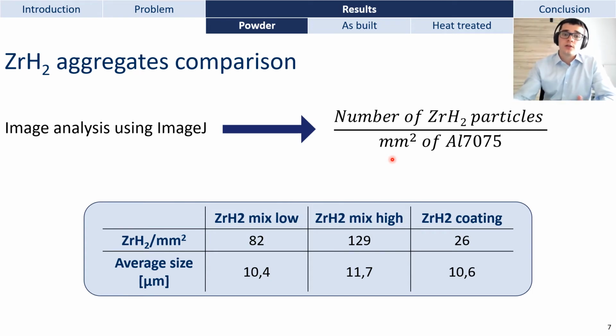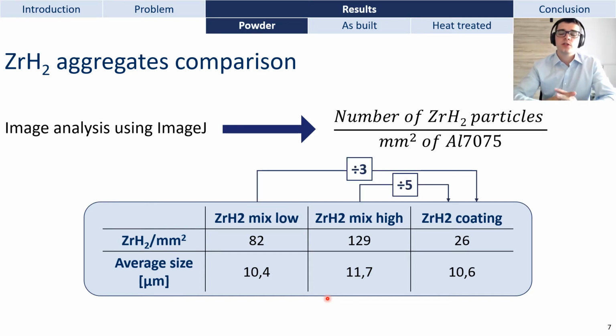We are also computing the average size of these particles, and you can see that for the three different alloys, it is roughly the same, around 10 microns, corresponding to the size of the zirconium hydride powder. What is really interesting there is that the zirconium coated powder exhibits respectively 3 and 5 times fewer particles than the low content mix and the high content mix powders. It shows that the plasma coating successfully limits the number of these unwanted particles, even though the zirconium hydride powder used was not sieved before the plasma coating.